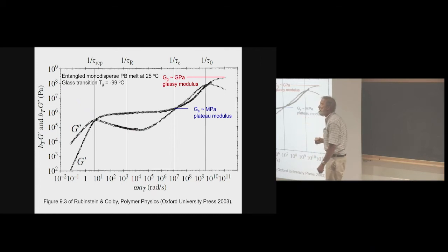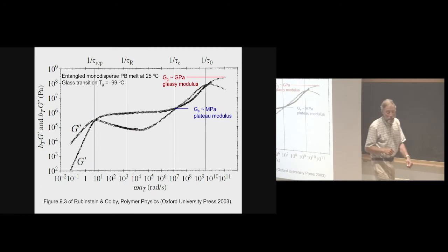So at that end, you're basically probing these really small segments of the chain? Yep. So back here, it's too fast and nobody gets to move. Then monomers start moving, and as more and more monomers move, we get all the way to what's called the Rouse time of an entanglement strand, and all that stuff gets to relax, basically. Yep. Great question.